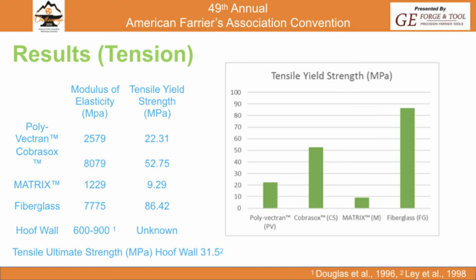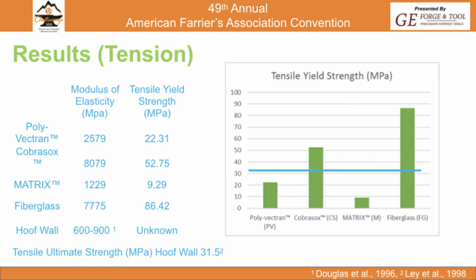So when we look at ultimate strength of hoof wall, that is when we know for sure it fails. You know, that's the strongest point, that's the most stress you can put on it before it fractures. So if we know the ultimate strength of hoof wall, then we know as long as our yield strength of our repair material is greater than the ultimate strength of hoof wall, it should stabilize the hoof wall or prevent it from fracturing. And so when you look at these numbers, the blue line is what is reported as the tensile ultimate strength for hoof wall. Okay? And so when you look at these, only 2 of the composites were greater than hoof wall.